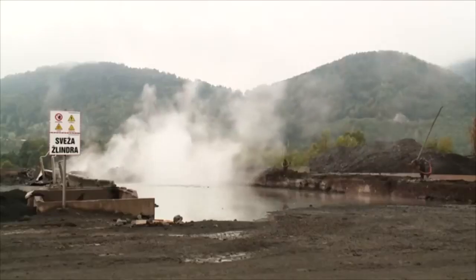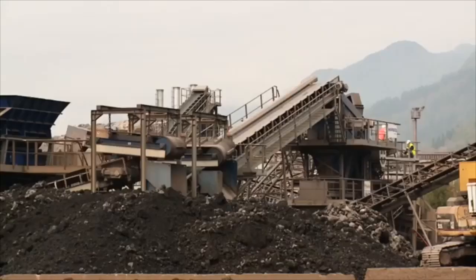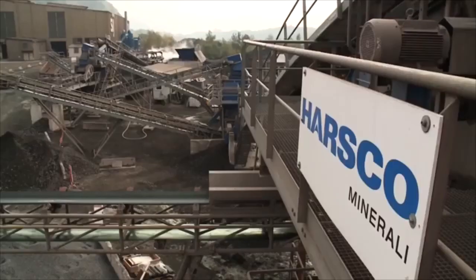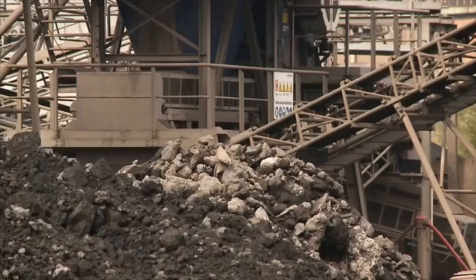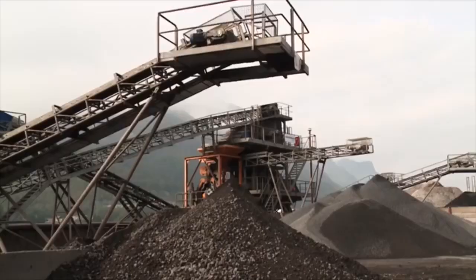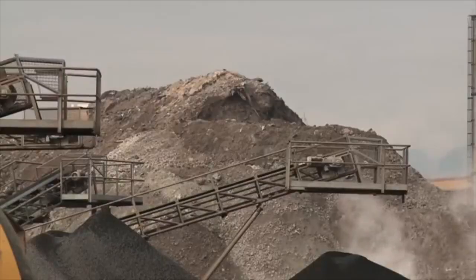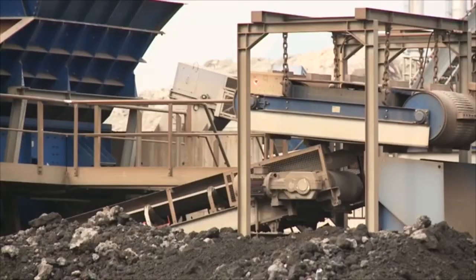Here, the first stage of the aging of the slag takes place, which consists of 2 weeks of wetting and mixing. In this way, the slag cools down slowly and in a controlled fashion, and its suitable microstructure is achieved. A transition of the unstable minerals into stable forms also takes place. The cold slag is then moved to a more distant waste depot, where it is left to age for a further 30 days.